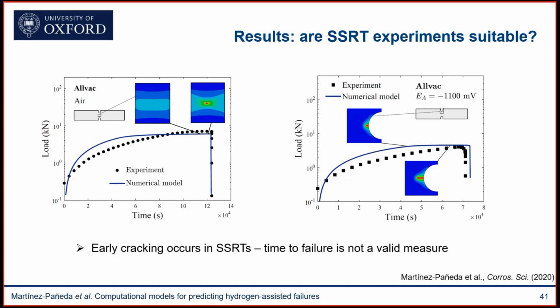So we took our model. First, we showed that the model was able to capture the failure time in the absence of hydrogen. We then introduced hydrogen for multiple environments, and we were able to show that the model was able to capture the failure times for multiple environments and multiple types of the K500 alloy, which is the alloy that we're interested in here.